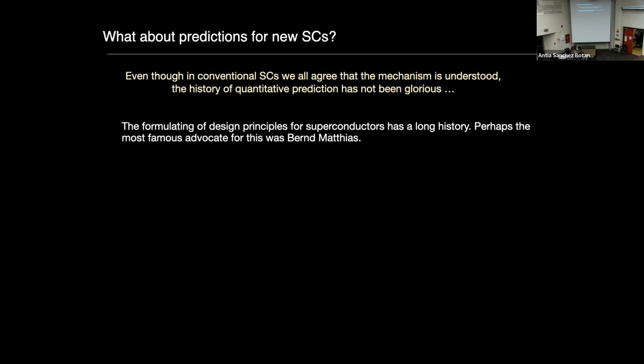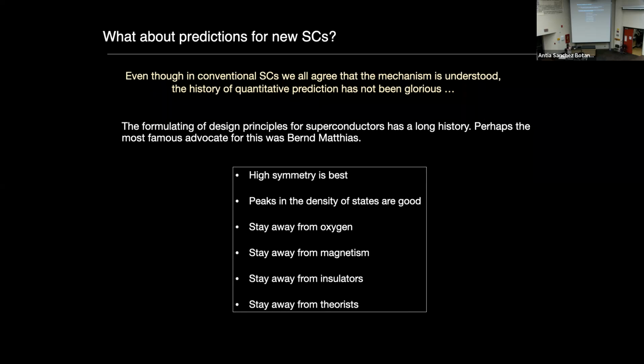new superconducting materials. And perhaps the most famous set of rules are those that were set by Bernd Matthias, who was an experimentalist himself. And his rules were the following: high symmetry is best, peaks in the density of states of the material are good, stay away from oxygen, stay away from magnetism, stay away from insulators, and probably most importantly for him, stay away from theorists. So hopefully, as a theorist myself, I'll show you today that we have some use, but he had his good reasons to think in this way, and I think he ended up discovering over 1,000 superconductors himself, actually.